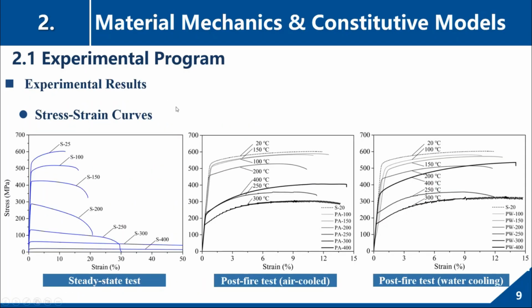So we got the stress strain curves of all of the specimens. For the steady state tests under high temperatures, the stress degrades clearly when the temperature increases. But for the post-fire tests, the data scatter much more notably than the steady state tests.